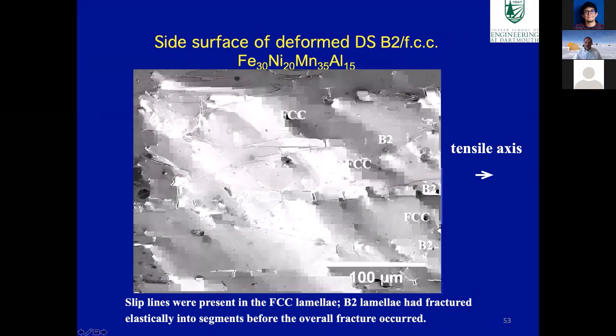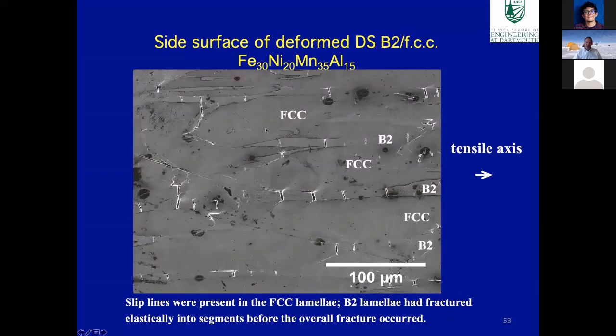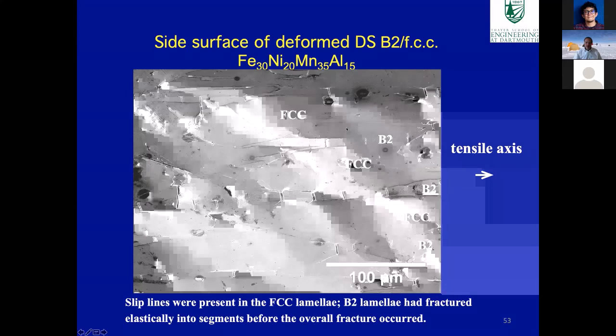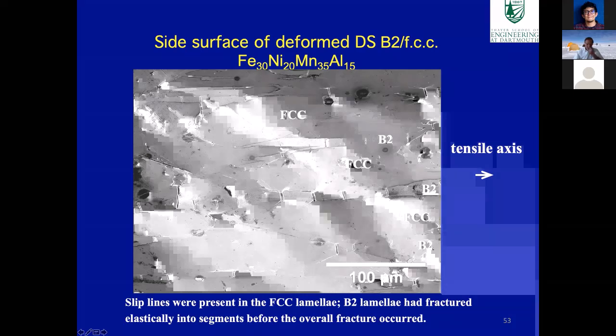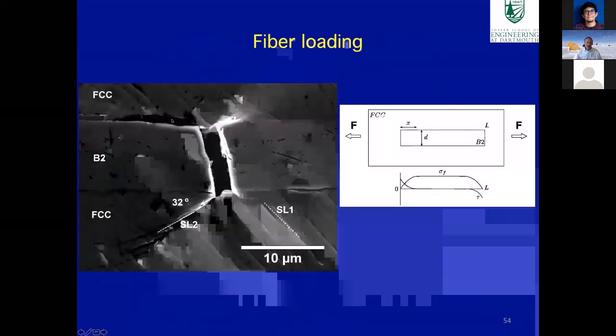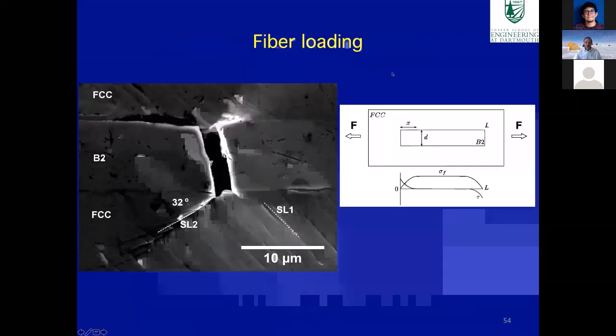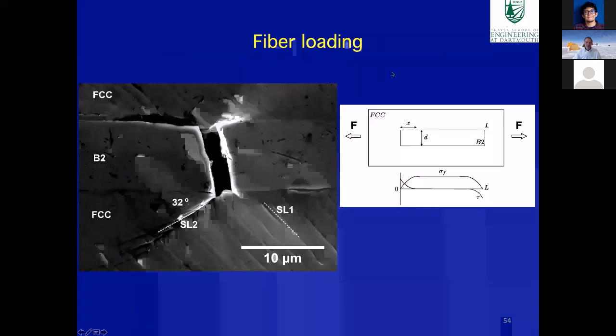If you look at a cross-section of a specimen strained to failure, this is the directionally solidified material, in which there are very large grains of material. You can see this is the FCC matrix, and these are the B2 grains. You can see the B2 grains actually fractured. It's almost like you've got a fiber composite with B2 fibers in an FCC matrix. If you look at higher magnification, you can see this sort of fracture behavior in the B2. We model this as a fiber composite.